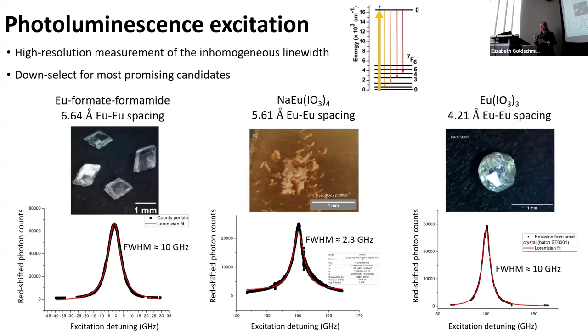One is one of those first ones that we grew, that metal organic framework, europium formate-formamide, where we can see this 10 gigahertz inhomogeneous line width when we do our photoluminescence excitation. That's bigger than a standard doped crystal, like a europium doped YSO crystal, but with 1,000 times the europium density. And in the doped crystals, your inhomogeneous line width goes with density, because that's the primary defect. So our spectral density here is a lot higher than in our typical doped materials.